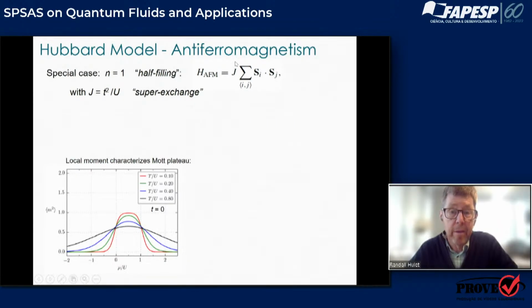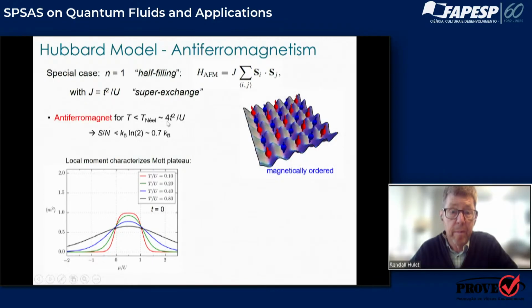So there's a special case of this Heisenberg approximation to the Hubbard model, which is that at very low temperatures, temperatures that are less than this super exchange energy scale, which for us is of order tens of nanokelvin or so, the entropy per particle will drop below log 2. Log 2 is pertinent because it reflects the fact that the entropy is due to the spin degree of freedom, the particle being up or being down right at the Néel transition is essentially equal. And when you go below the Néel temperature, you're also going below the entropy of log 2 per particle.